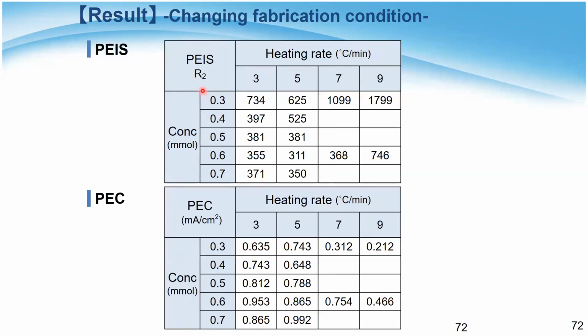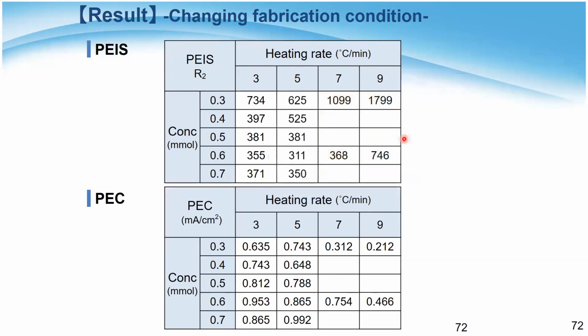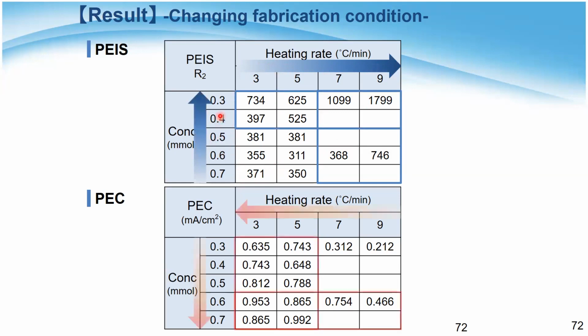And finally, the R2 value was also selected. R2 is the resistance at the solution interface. And this one is positively correlated with heating rate, so resistance increased as the heating rate increased, and it decreased as the concentration increased. So this is negatively correlated with concentration, so a smaller heating rate is better, and a higher concentration is better. So again, R2 is also an important descriptor.